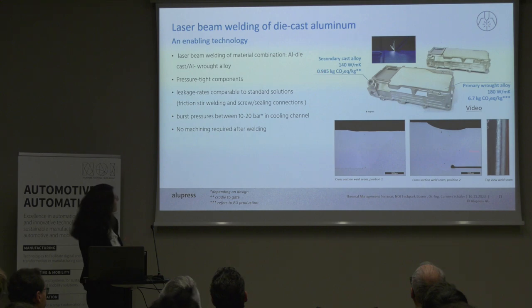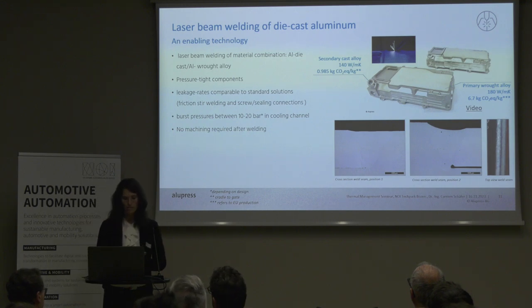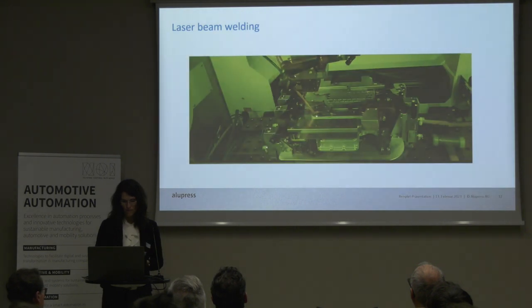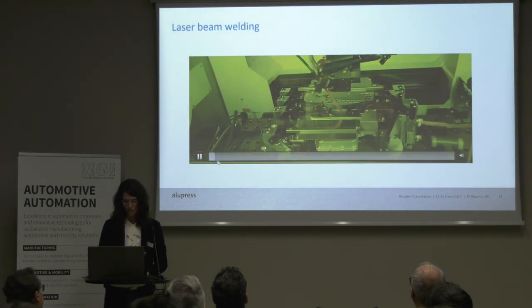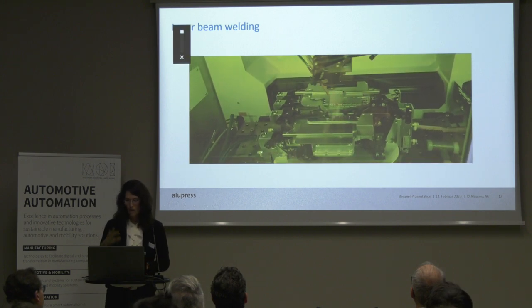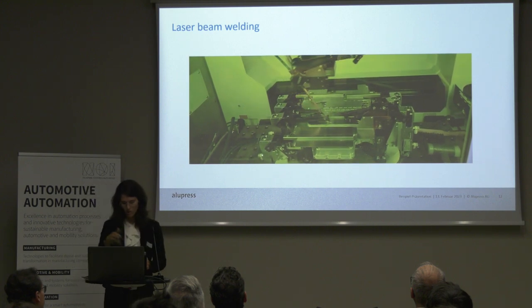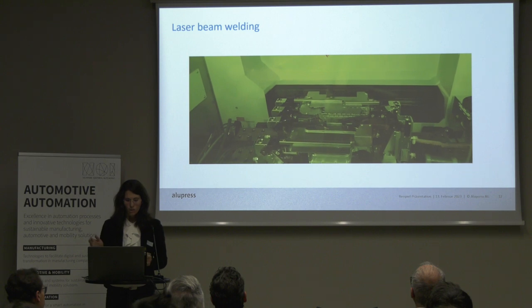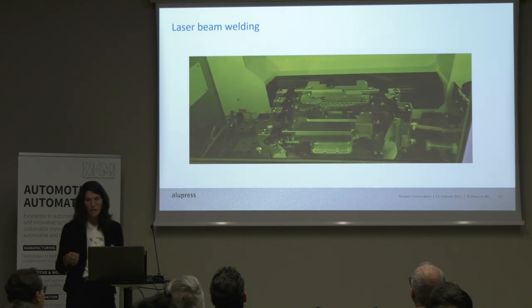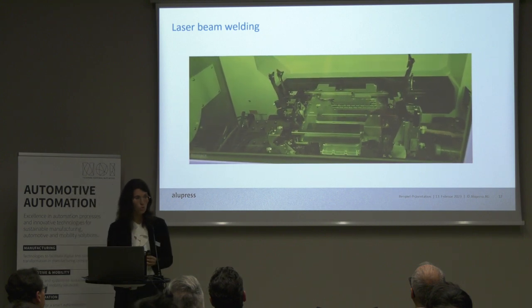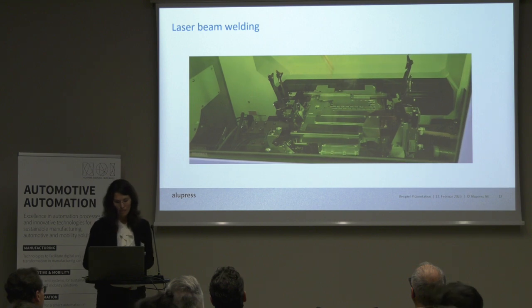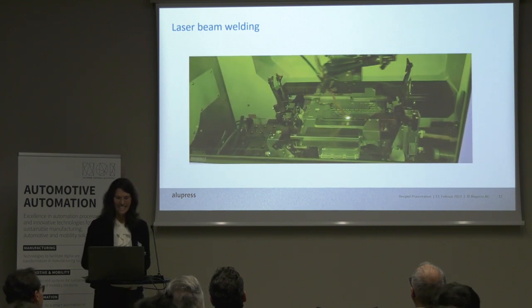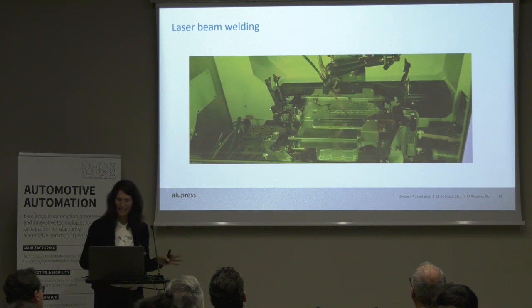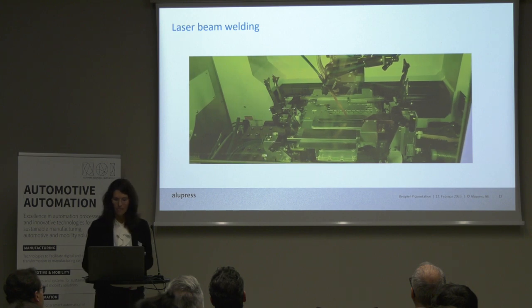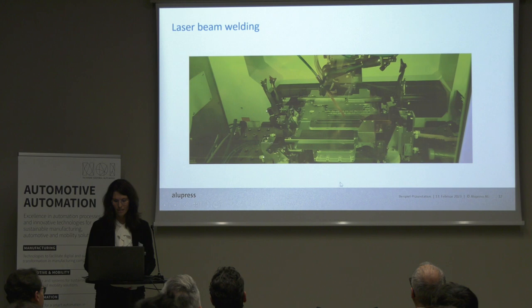So what we can do with laser beam welding, and I'll show you just a movie, is we can combine this. We get pressure-tight components with very good leakage rates, and we do not have to do machining afterwards. See if this is running. So this is now still a prototype process; in production, it's running much faster, because you will see some stops in between the welding now. In total, this component is welded in 30 seconds, and the competing technology of friction stir welding takes at least 1.5 to 2 minutes. So depending on the alloy, we have an improvement in velocity by a factor of 5 to 10. And this, again, brings down our costs. And I can tell you, in die casting, it's really not easy to do this. But we have managed it now.